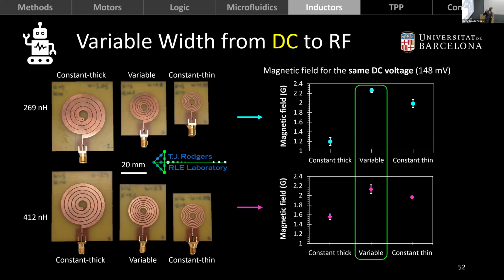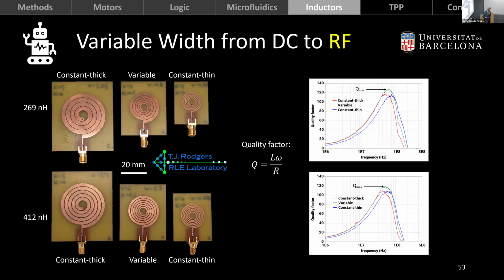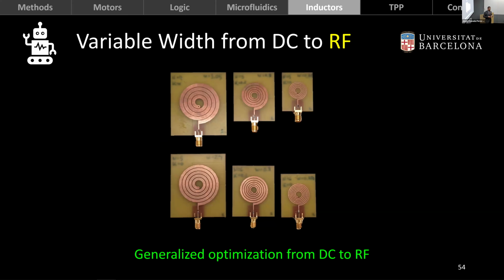And this means that we can actually implement this, take it to our 3D printed solenoids and potentially improve their performance by means of leveraging this behavior. And when looking at the RF performance, we focused on the quality factor as a metric, which basically is the ratio of the energy stored in the magnetic field over the resistive losses of the devices. And we were very happy to see that the quality factor of the variable width inductors basically envelopes those of the constant width inductors. So we are effectively getting the best of both worlds. And so with this, we have come up with a generalized way to optimize planar inductors for DC all the way to RF.